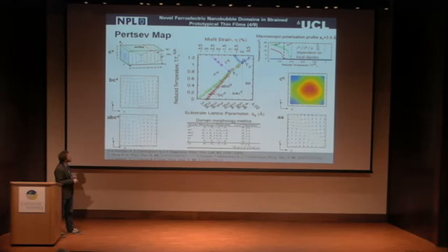What we find in the high tensile strain, we get these AA domains here, which are these 90-degree domain patterns if you're looking down from the surface. Equally, it can also be facing along the 110 direction. So using our definition here, so long as the macroscopic polarization is along 110, that seems to satisfy this rule. If we go into this high compressive region, we get what we call CD domains, which are these Landau-Lifshitz looking closure domains, which have these 180-degree domain walls with these 90-degree domain caps. If you make it thinner, agreeing with the work by Sylvia Tinte's group, this reduces down into a vortex, so you get these vortices.